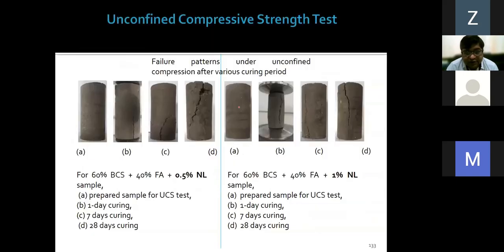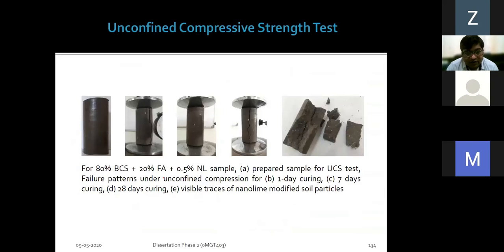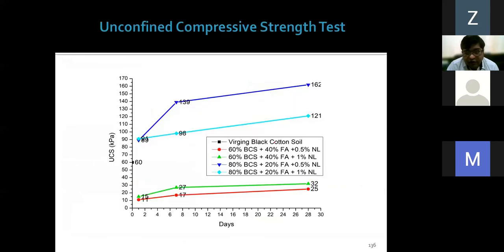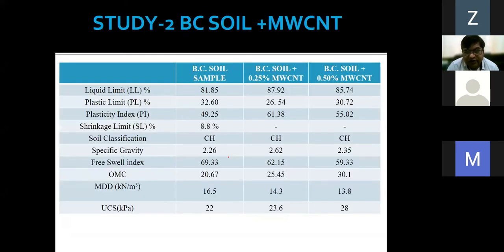Likewise, unconfined compressive strength was also tested on the various specimens, and we found that unconfined compressive strength also increased drastically. So that is the area we are working in. Then we found that no researchers were working with carbon nanotube